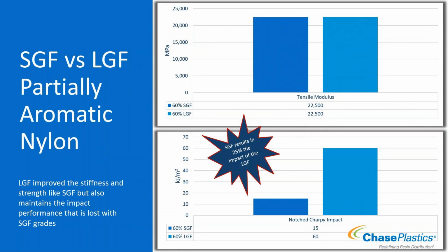Now, when we look at our impact values, we use Charpy notched for this, which is what's on the data sheet to compare. The Charpy notched impact for the short glass fiber is 15 kilojoules per meter squared, compared to the long glass which is 60. So your short glass is only 25% of it—or to say it another way, your long glass fiber has 4 times the impact that the short glass has. Huge loss of impact when you use short glass that you don't see with long glass.